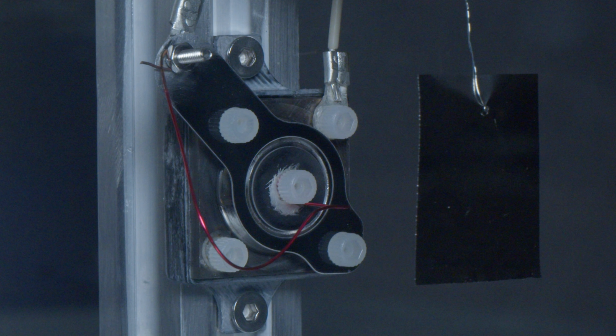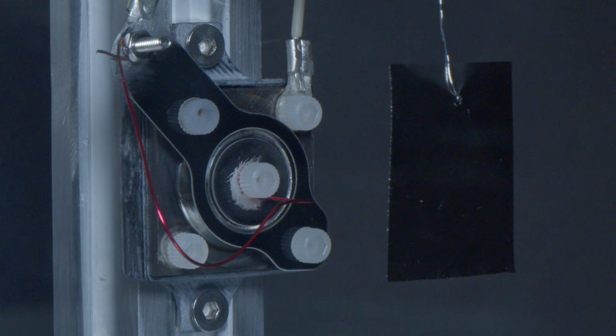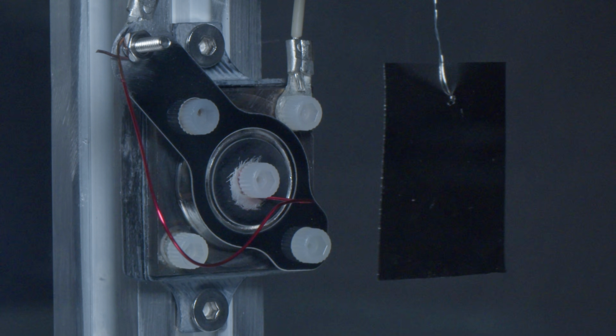My final iteration on this was to put the central electrode back, but connect it by a long wire instead of bridges. So this should hopefully avoid the bridging issue, because there's nothing directly above the slot anymore, but keep the field strength high by having both an inner and an outer electrode. Unfortunately, I couldn't get this to work either, for much the same reasons. Either nothing happened or it would start to arc.